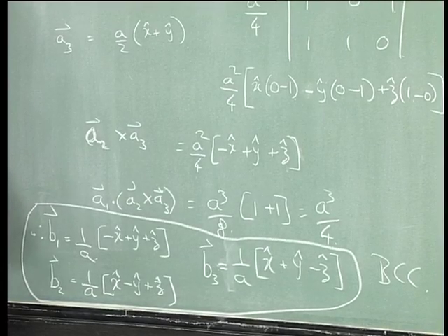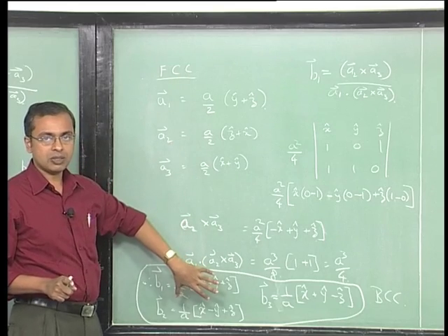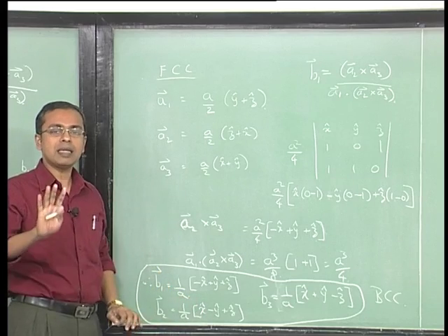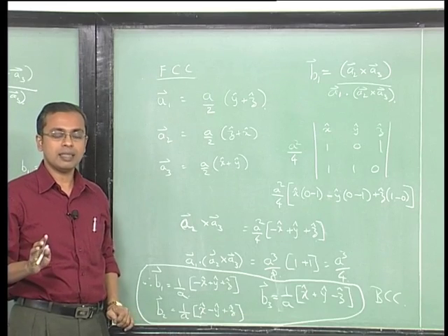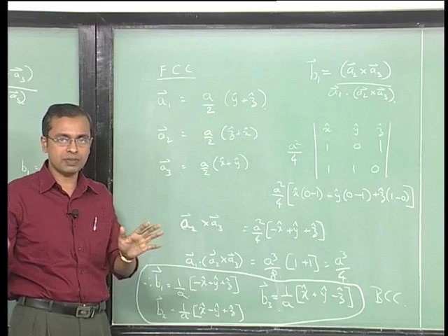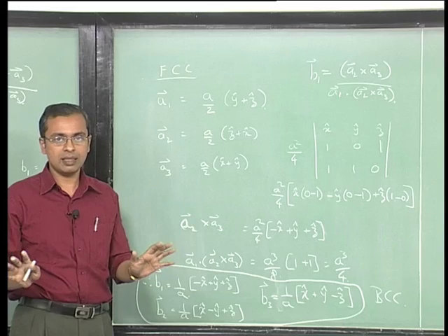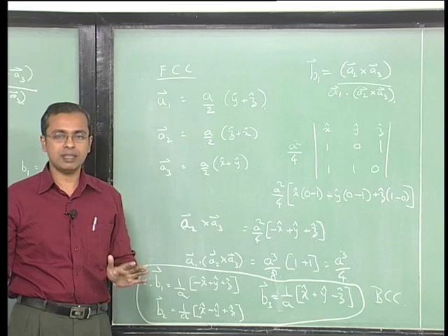The geometry that was face centered cubic as we started out with, when we converted that to a reciprocal lattice notation, it became body centered cubic. Please keep in mind, as I mentioned right at the beginning, this is only for our convenience, just a notation we use to serve some purpose. The material is still face centered cubic, nothing has happened to the material. It is not that the material suddenly became body centered cubic.